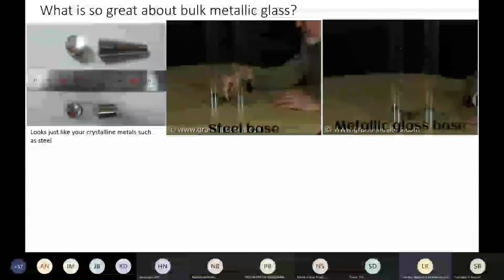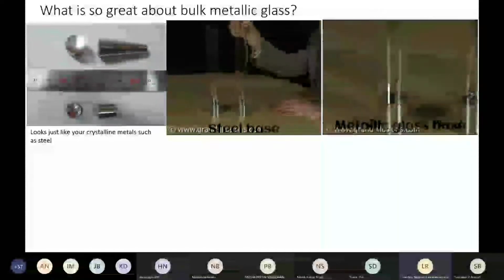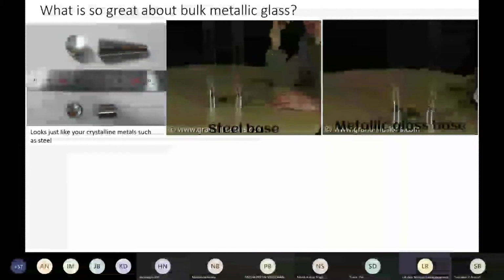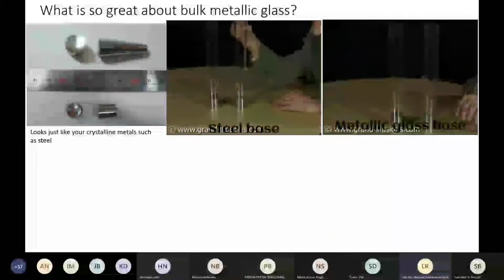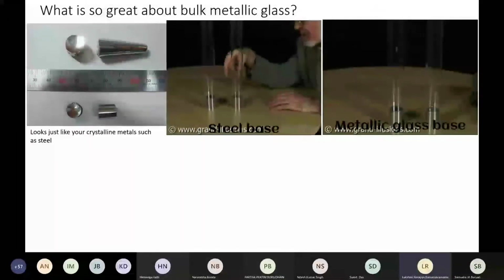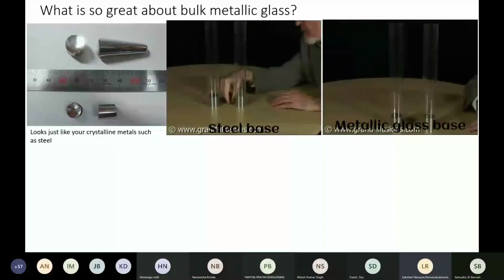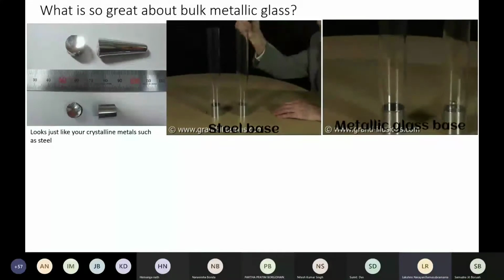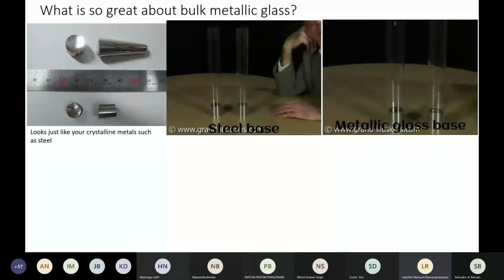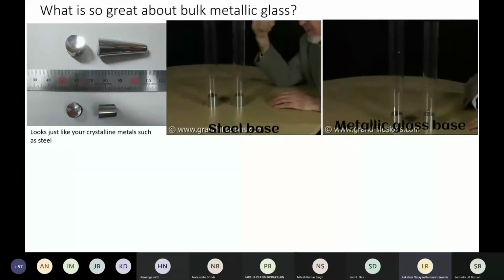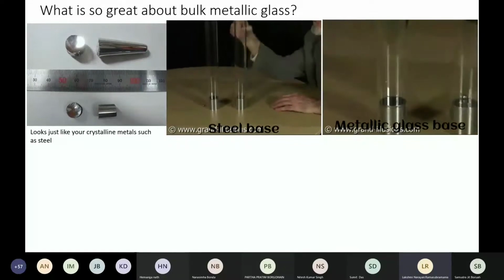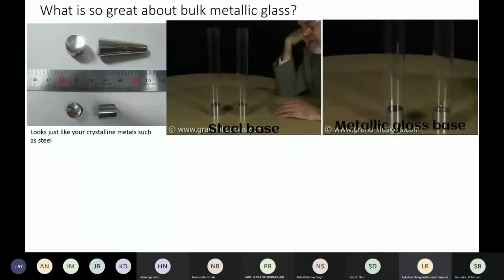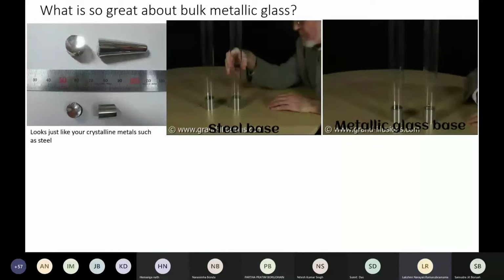You might have heard of this thing known as coefficient of restitution, but coefficient of restitution is not surface dependent. In this case, it appears that metallic glass offers a greater coefficient of restitution, or in other words, the kinetic energy of the ball is being completely returned back to it in an ideal situation. So metallic glasses are able to absorb the energy and immediately release it back to the steel ball.